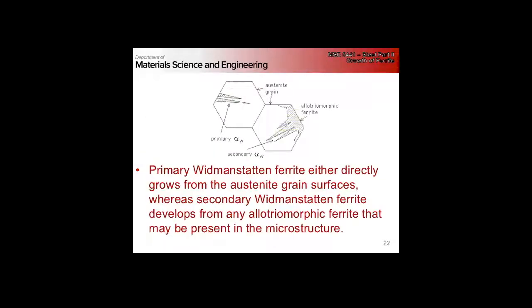So we have two basic classes. We've got primary Widmanstatten ferrite that grows directly from the austenite grain boundaries, and then secondary that grows from any grain boundary ferrite that happens to be there - so any allotriomorphs of ferrite that happen to be there.